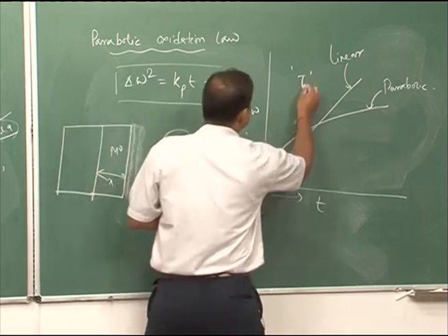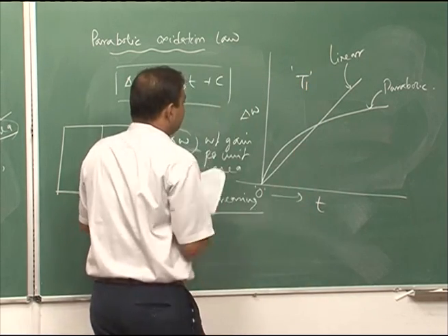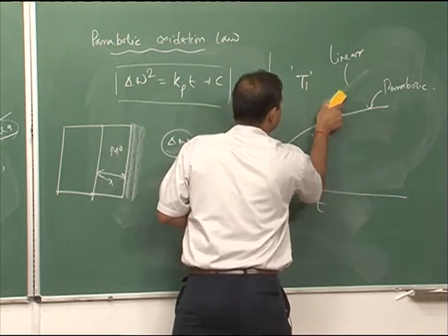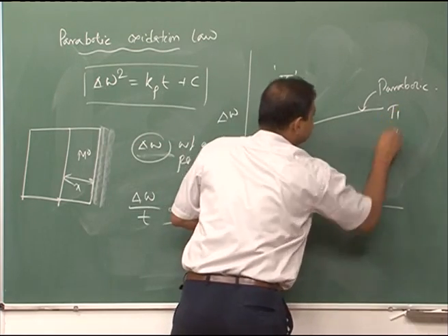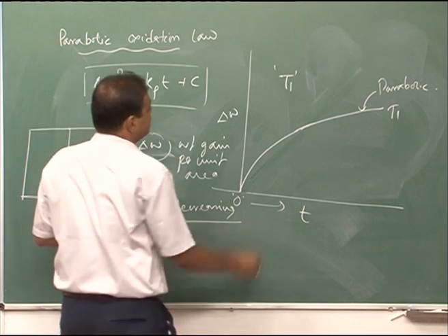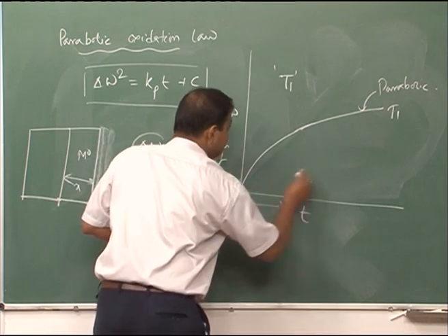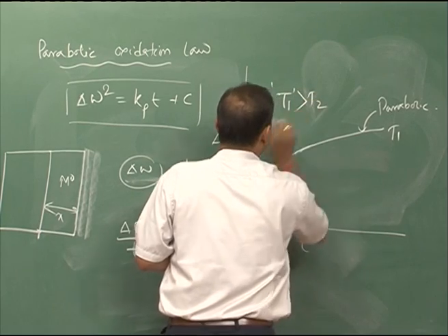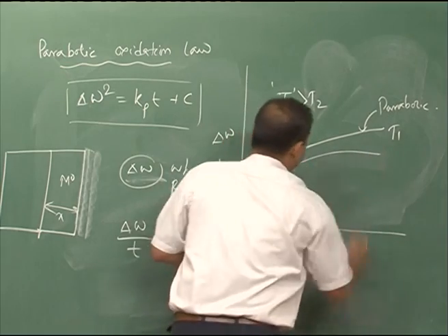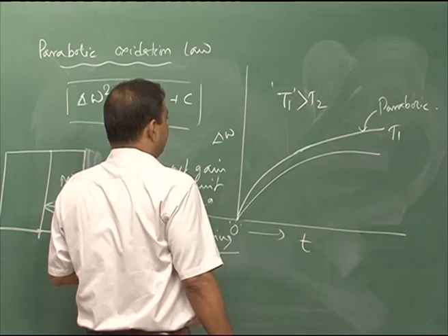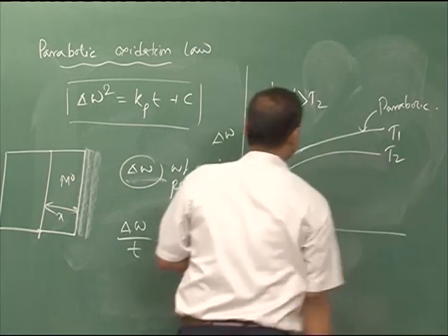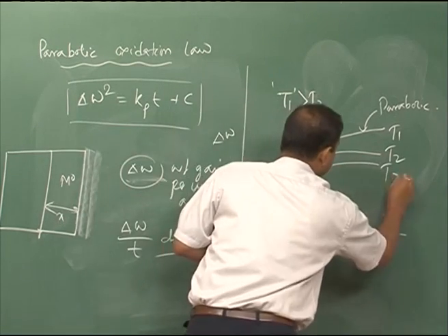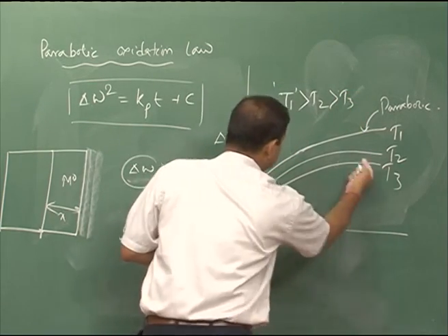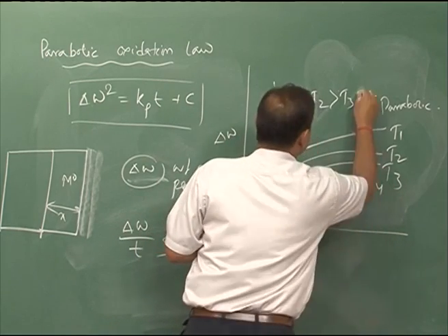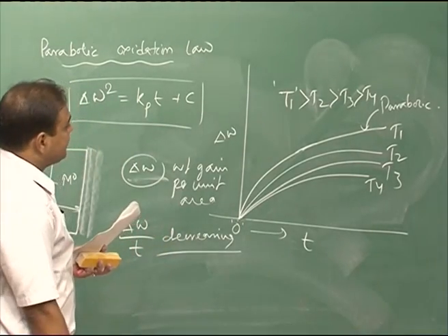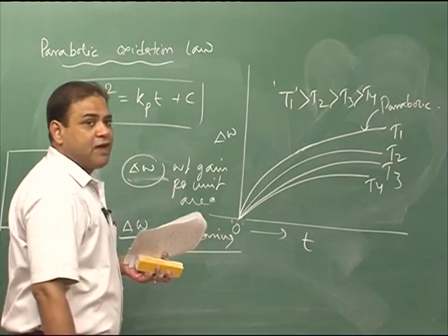Now, let us say the parabolic oxidation is happening at temperature T1. Then in the second case, if I would like to do it at a different temperature T2, and if T2 is less than T1, your rate of weight gain would be less compared to the oxidation happening at T1. So, this is at T2. Secondly, if we consider T3, this would also be low, and then if we consider another temperature T4, we can find out from this simple experiment the value of the activation energy.